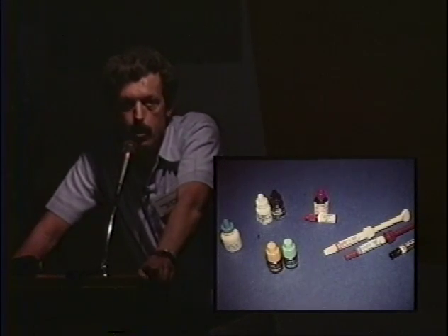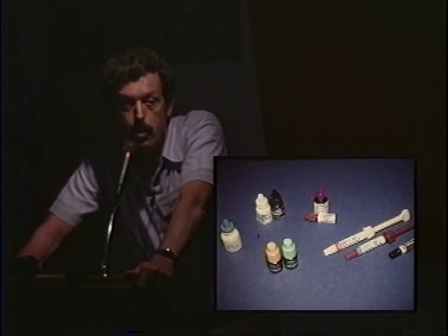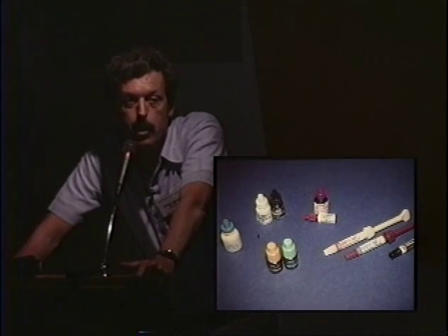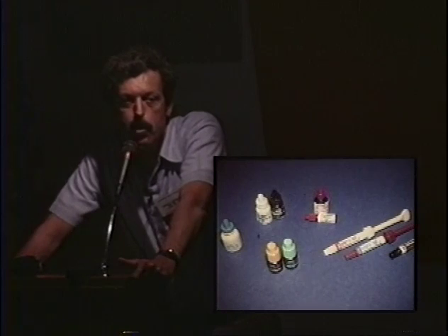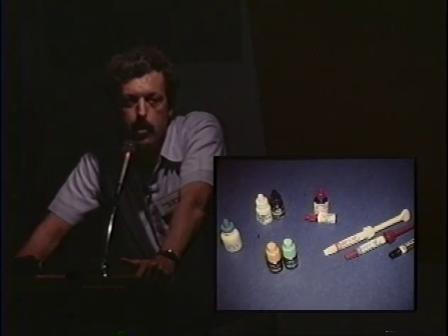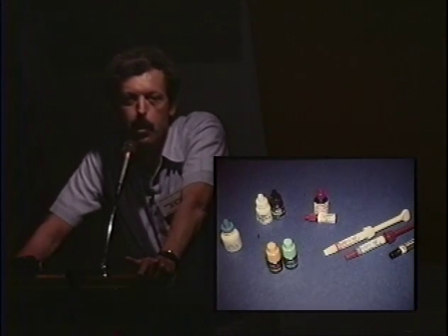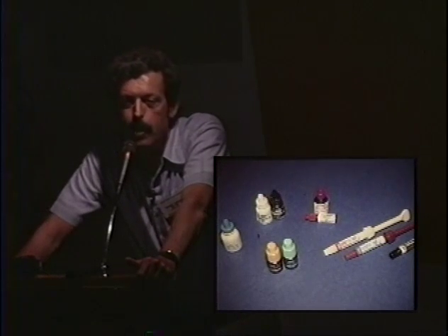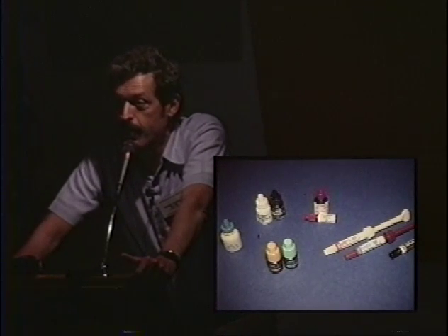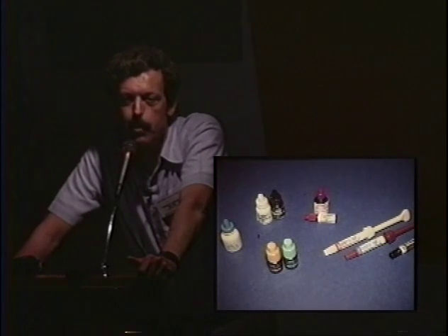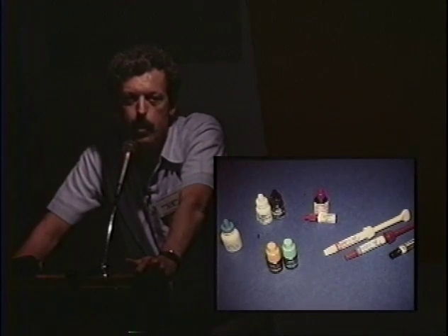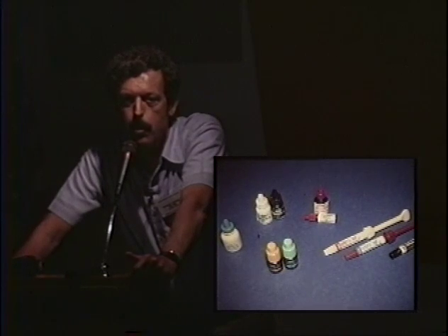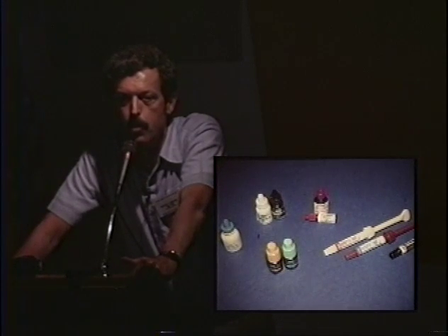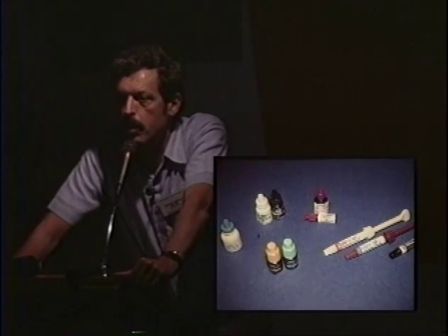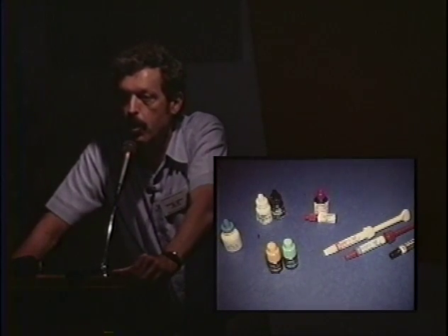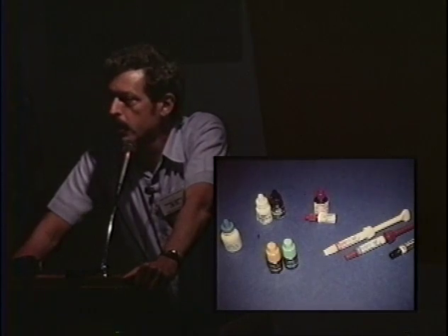You don't have polymerization. You know, monomers are toxic to the pulp. It's polymers that aren't. So you can put HEMA, hydroxyethyl methacrylate, in your eyeball. That's polyHEMA. That's a soft contact lens. But if you put it into the pulp, it'll kill the pulp. When you polymerize it, it's fine. Pretty interesting, huh? You want to polymerize these things. You don't want a bunch of free monomers cruising around. You want polymers there. That's where some of the pulp biologists have made a big mistake. They test monomers, not polymers. And you're not putting monomers in a tooth, you're putting polymers in there, hopefully. Okay. Any other questions there?